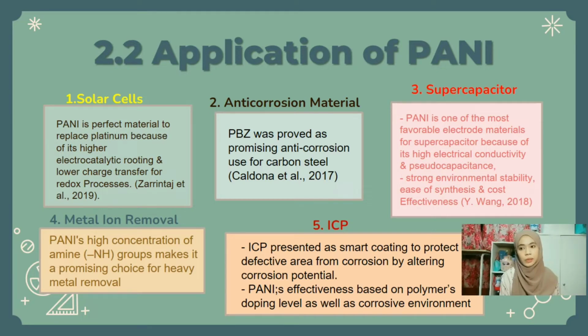For anti-corrosion material, polybenzoxazine (PBZ) has a low shrinkage, a low surface free energy, low water absorption, and good thermal and mechanical properties. PBZ protects steel on its own, but its combination with PANI outperforms the pristine PBZ in terms of protection. So PBZ was proved as a promising anti-corrosion use for carbon steel. In supercapacitor, PANI is one of the most favorable electrode materials because of its high electrical conductivity and pseudo-capacitance. PANI also has a strong environmental stability, ease of synthesis, and cost effectiveness.